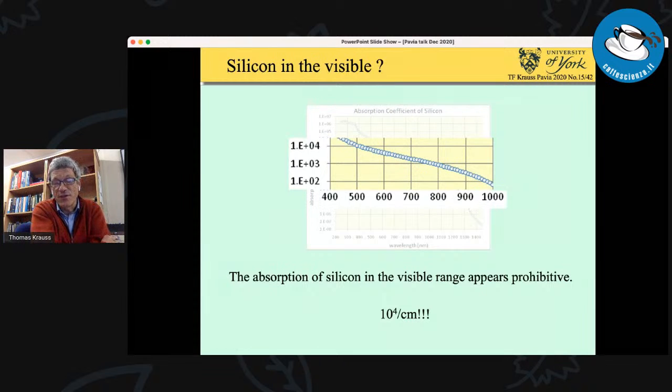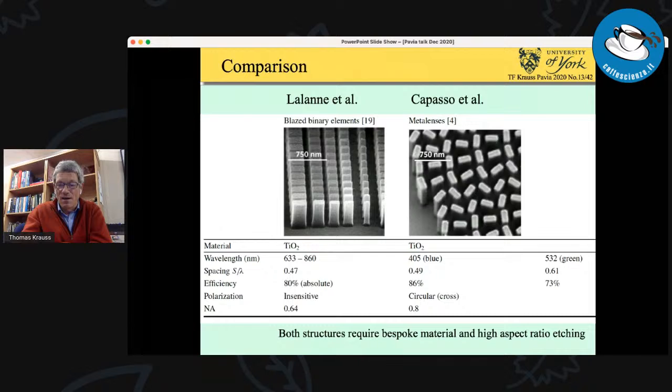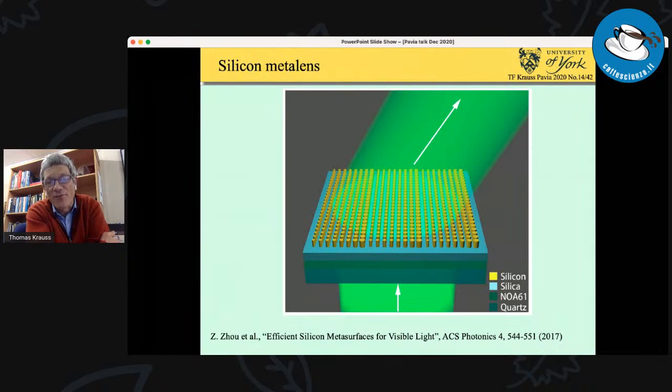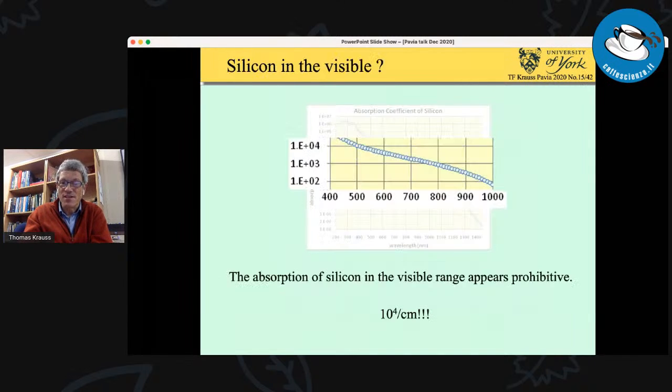And then if it goes to 250 nanometers of silicon, actually, it's only e to the minus a quarter, which isn't very much. And then also, you look at this, and you think, well, actually, half of the material is etched away. So now we're talking e to the minus an eighth, which is about 80-something%. So the loss starts to become very small. So actually, it's not such a bad idea to do this in silicon.